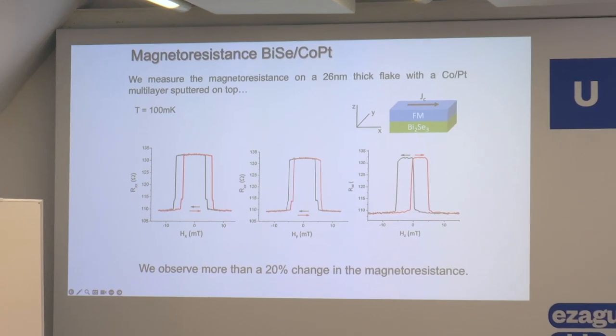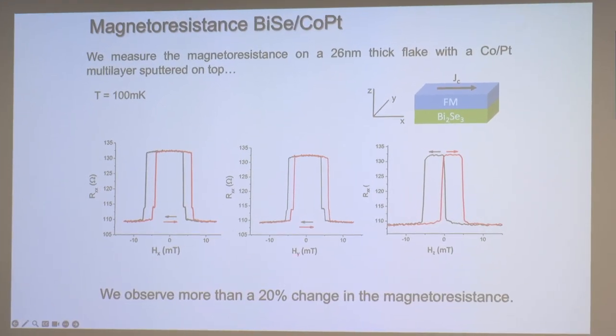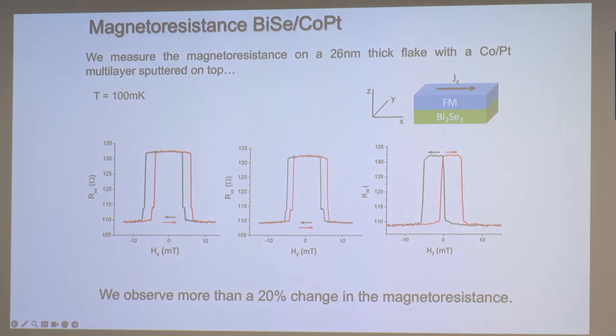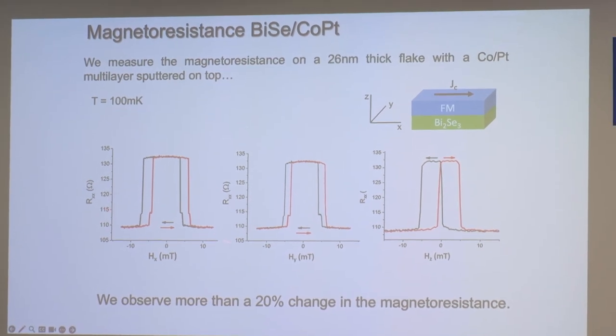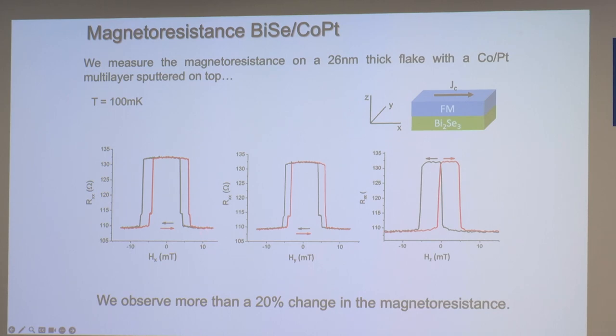Okay, so in this case, we again took a 26 nanometer thick flake of bismuth selenide. We put cobalt platinum multilayer on top. And what we observe is a 20% change in the magnetoresistance. The field scale here is much smaller than what we saw with the YIG. Okay? But in this case, we can see that at about 10 millitesla, we get this hysteretic switching with a very large change in magnetoresistance, again, much larger than what you'd expect from AMR, any sort of other change of the magnet alone. And what was interesting here is you see that the switching occurs for all field directions.